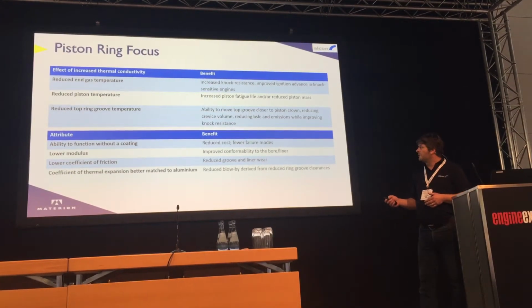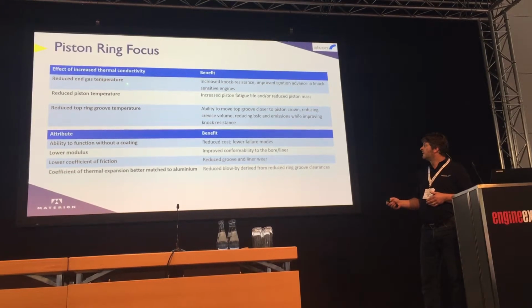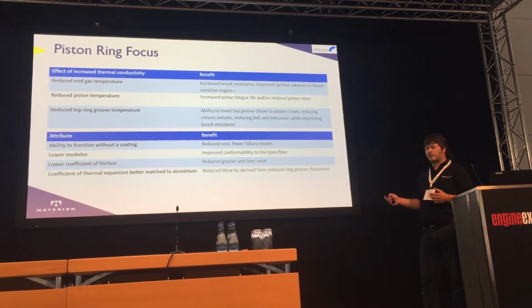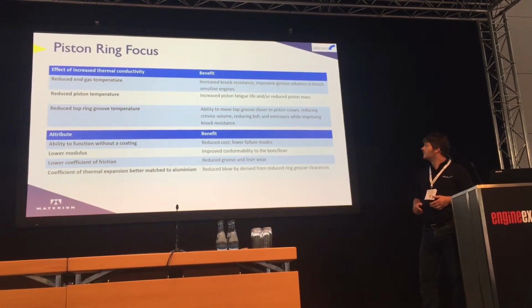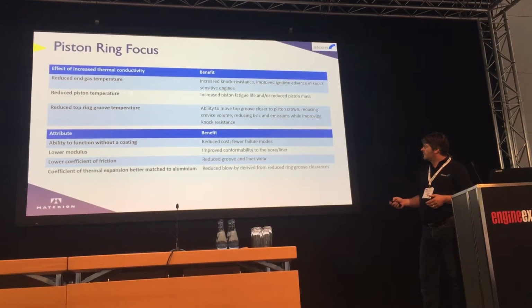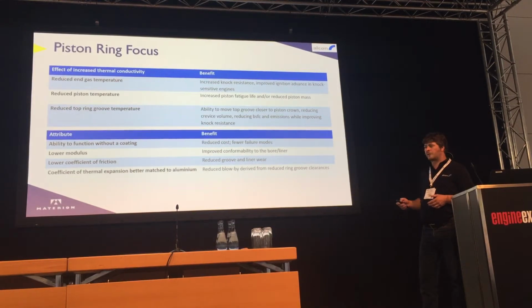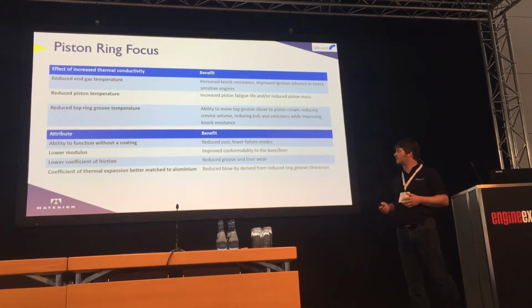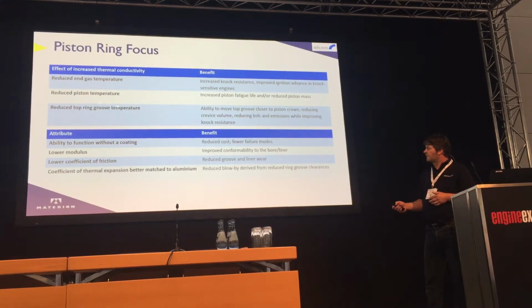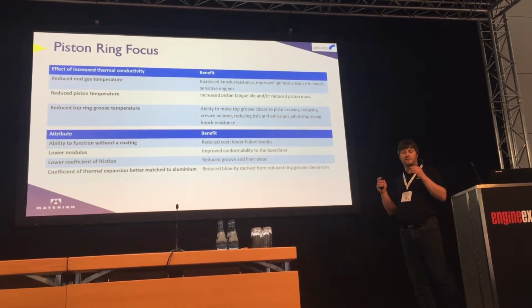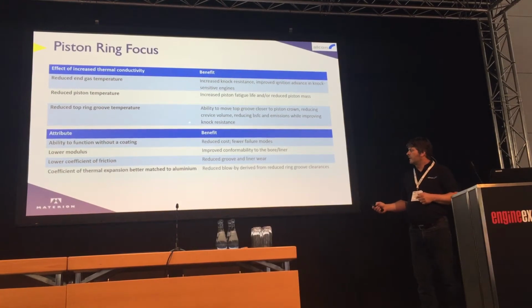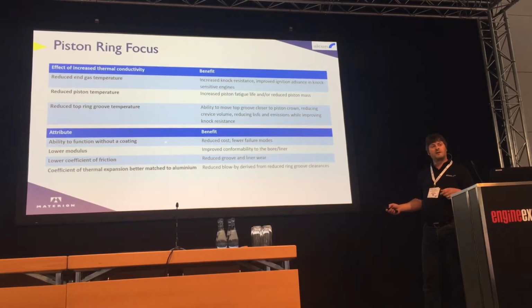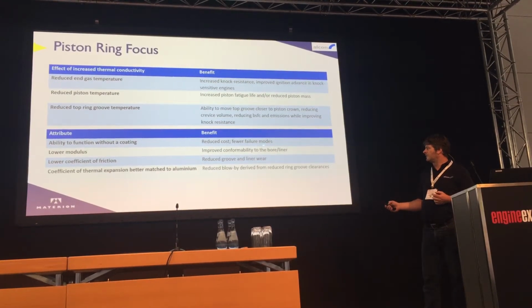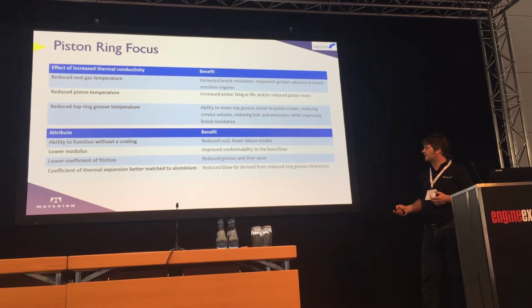So why were we doing it? We're looking at reducing the end gas temperature, basically, and especially on high specific engines or ones that are boosted, we're looking at basically increasing knock resistance. Reducing piston temperature again, improving fatigue life, so again you can make the piston lighter if you can reduce its temperature. Reducing the top ring groove temperature allows us to push the piston ring up even higher and reduce the crevice volume. Other attributes are there's no coating required with the ring, so it's a ring that's monolithic. You remove a failure mode and potentially reduce the cost as well without a coating.